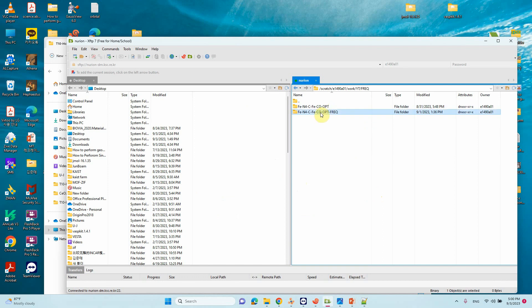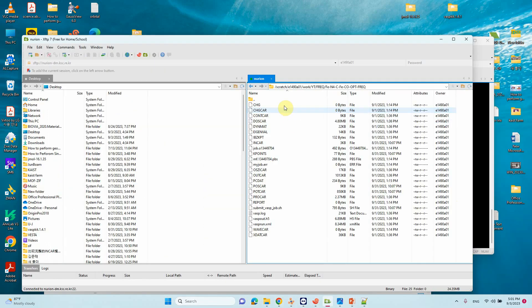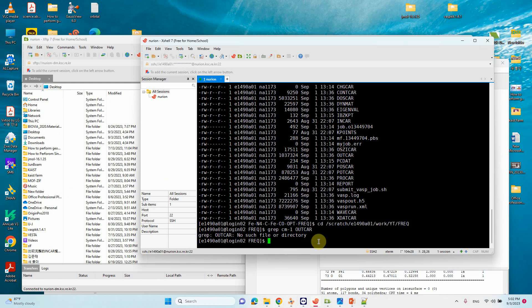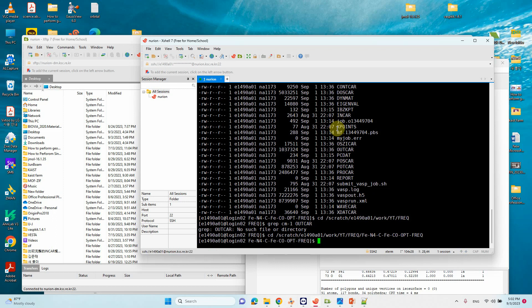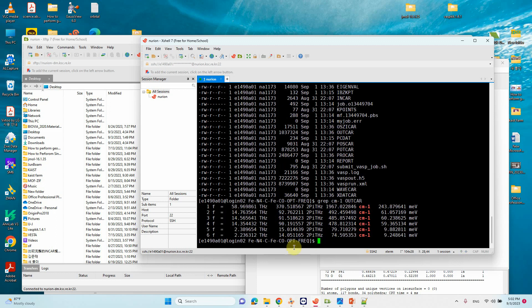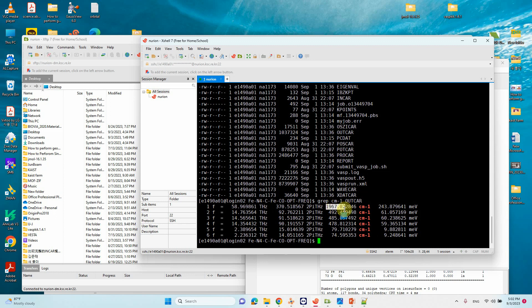I already completed the optimization and frequency calculation. To inspect the output, navigate to the frequency output folder and list all files. Type: grep 'cm-1' OUTCAR — this will extract the cm⁻¹ frequency lines from the OUTCAR file. You can see the vibrational frequencies of the adsorbed system. The key CO stretching frequency here is around 1967 cm⁻¹.